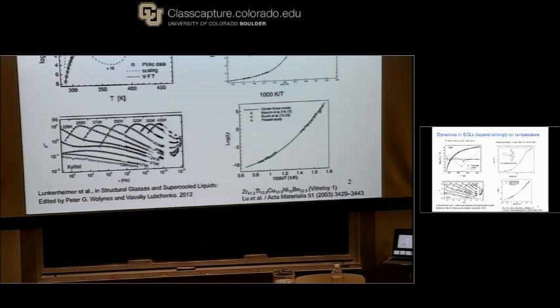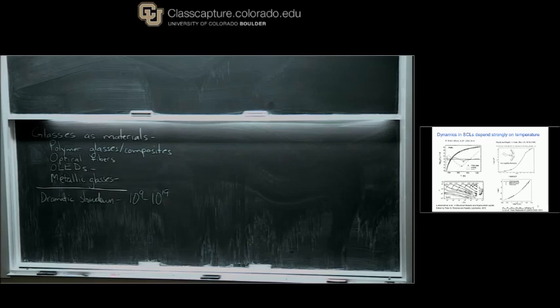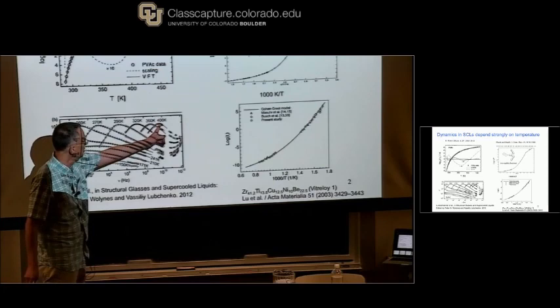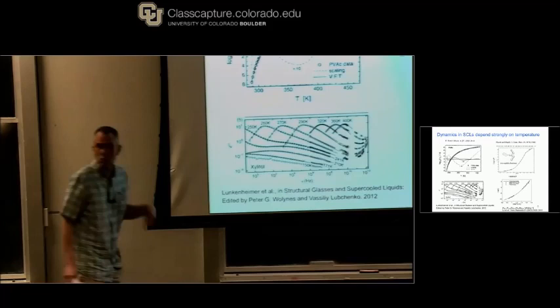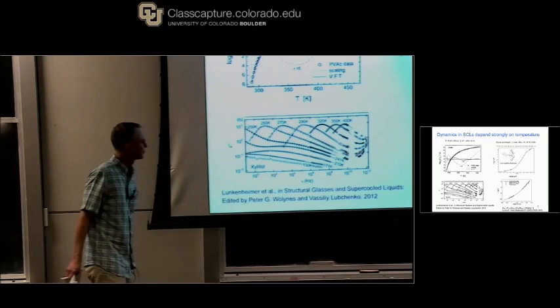So to the slowdown part: this data shows a slowdown with temperature of a minimum of nine orders of magnitude and up to 19 orders of magnitude. This is a dielectric relaxation spectrum. To a first approximation, what you're measuring here is the timescale for dipoles to reorient. If you look at this peak at 400 Kelvin, reorientation is on the timescale of 10^10 Hz. Cool it down to 260 K, and we're down to 10^1 Hz — that's nine orders of magnitude of slowdown across that temperature range.